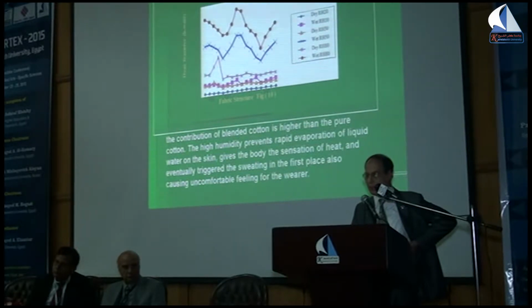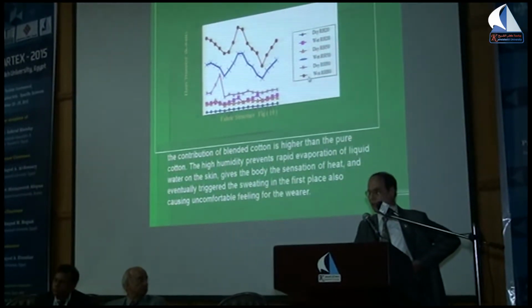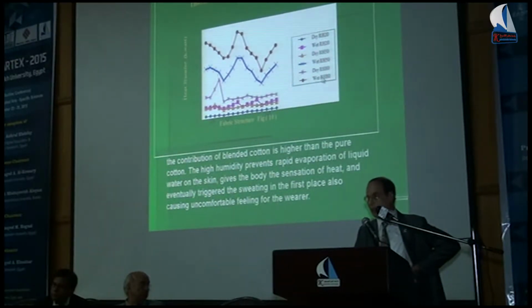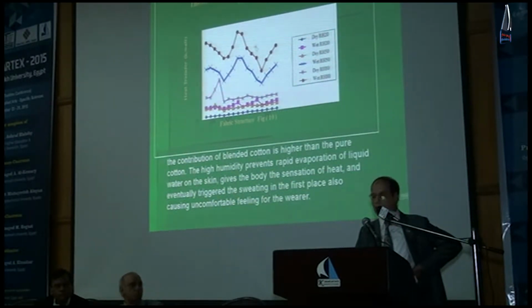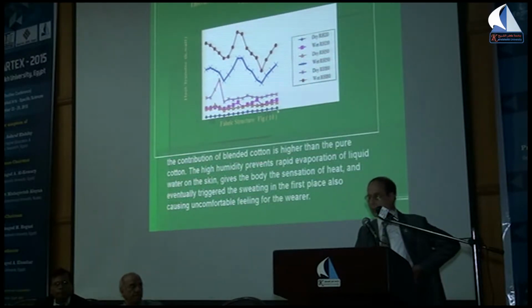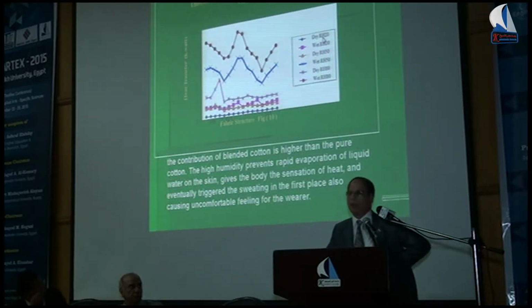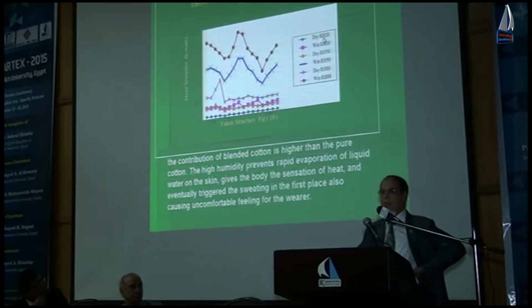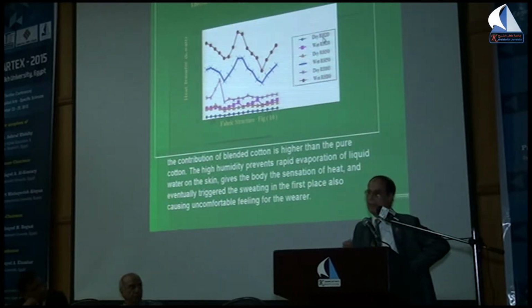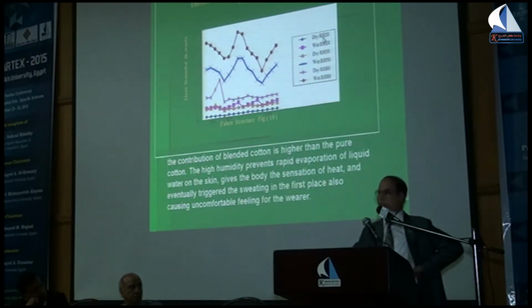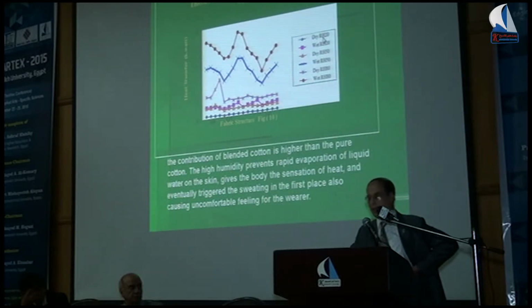We can find the same things. The most interesting thing is when the fabric is very wet, I mean completely wet, at relative humidity 80%, it gives the higher heat transfer. The lower one is dry at relative humidity 20. The contribution of blended cotton is higher than the pure cotton. In fact, this is very interesting because we know that polyester doesn't absorb water, but the porosity here is very high. The combination between the polyester and the cotton, the porosity, which really depends on how much absorption of water through this fabric, gives a very interesting result.